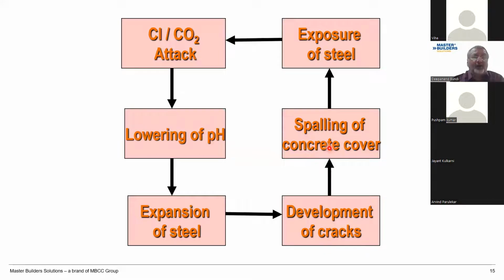Because of that, the concrete cover is going to spall, and when the concrete cover spalls, there is again exposure of the steel, because now the cover has gone, and there is a direct attack of chloride and carbon dioxide on the reinforcement bar. So if you see, this is like a circle that is going on. It will keep on going. We call it the vicious cycle, and that's where we need to step in and provide different types of protections onto the concrete surfaces.